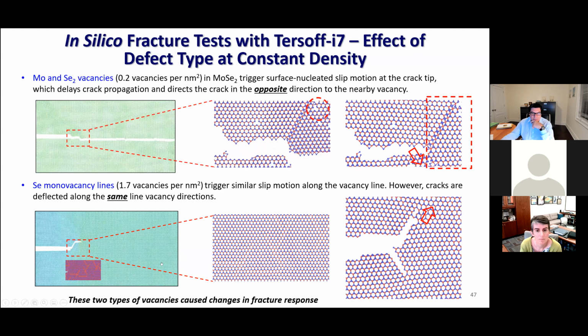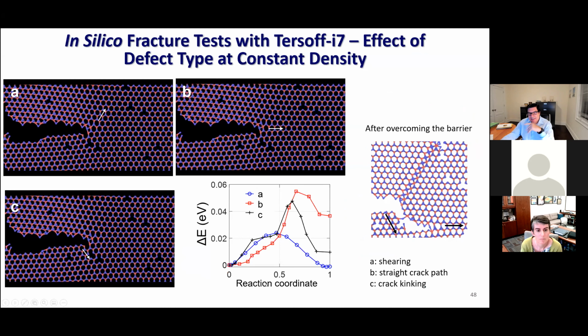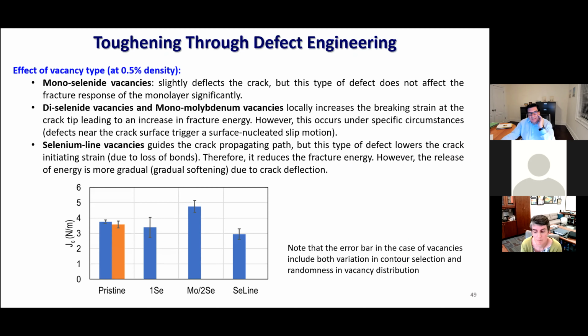And for line vacancies, the fracture process is much more complex. There is an explanation for this: when the crack arrested, why shear the lattice in this way. And again, you can do energy landscape to show that that's the most favorable way, and that for that environment, the crack deflection and so on. So everything can be explained in mechanics terms. But the key is that you don't gain a lot, in this type of materials, some of these TMDCs, by putting the vacancy. At the most, you get something like 30–40% increase in toughness for certain defect types.